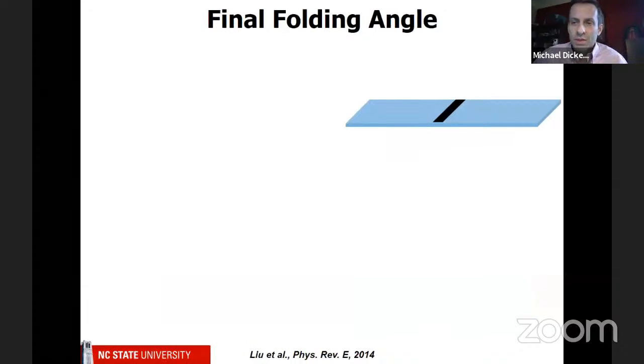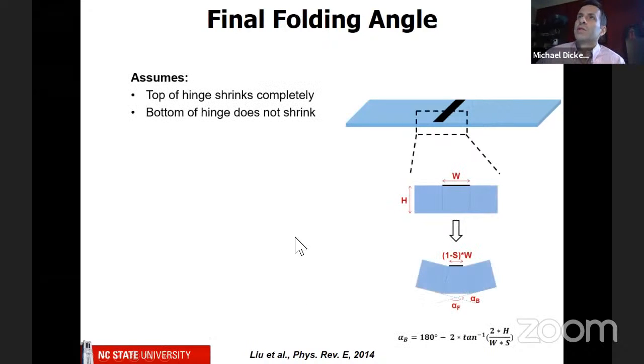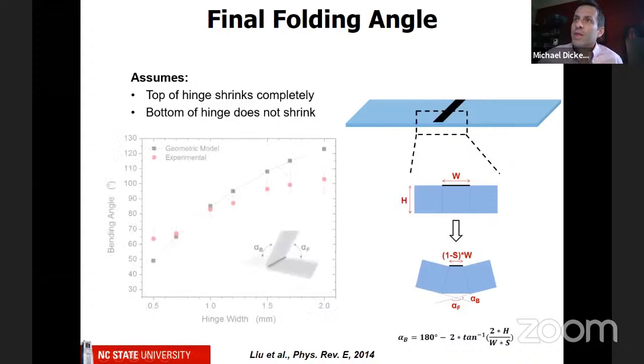Okay, so a couple details that I want to tell you about how this works. What we did is we said, okay, what if you want to control the angle of this thing, the way it folds? Well, we assume a couple things. First is at the top of the hinge where the black ink is, it will shrink completely, and the bottom hinge does not shrink at all. And when that happens, if this is a cross-sectional view, so this H is the thickness of your film, and W is the width of that black ink. So when the top part shrinks, it gets smaller and it causes the material to fold. And you can just use simple geometry to figure out what that is.